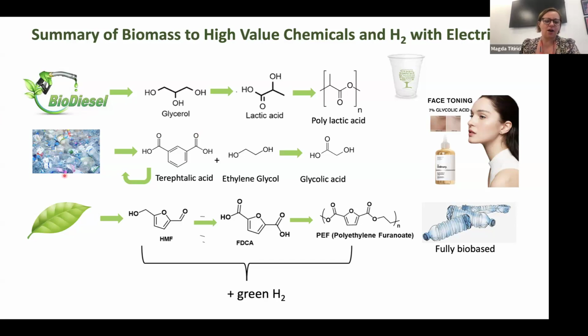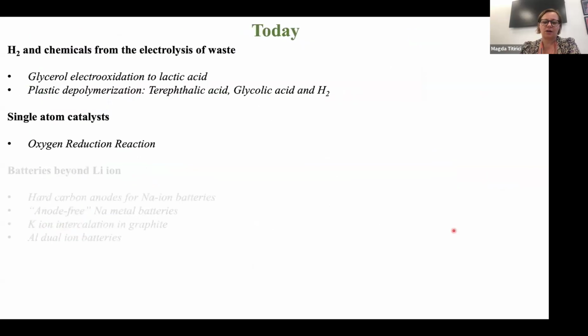Now, I also showed you how we actually take plastic waste and through some smart depolymerization and electrodialysis process, we turn this into terephthalic acid and ethylene glycol. And ethylene glycol we convert to glycolic acid, which again, a skin toning compound and gives you this wonderful skin. And then another thing I didn't show is that we also work on converting biomass to 5-hydroxymethylfurfural, which we then electrochemically oxidize to furan dicarboxylic acid, which is a precursor of making PEF, polyethylene furanoate, which is a fully bio-based PET. So this is our work on hydrogen production electrochemically.